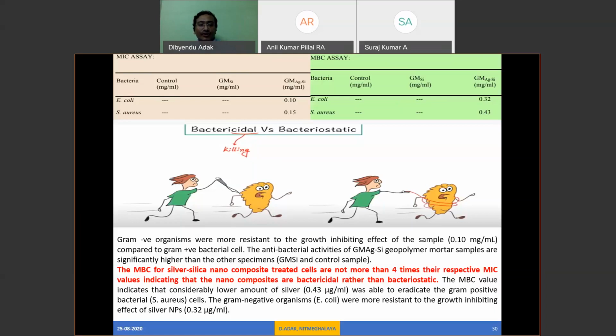So from this MIC and MBC, we can say that the silver silica nanocomposite treated cells have an MBC value not more than 4 times the MIC value. On these values, we can report that our nanocomposite is bactericidal rather than bacteriostatic. What is bactericidal? As I told you initially, the silver silica nanocomposite will kill the bacteria, whereas bacteriostatic means we can only make them stable and stop their rapid growth. Bactericidal means they will kill the bacteria. So from this MIC and MBC study, we can say that our silver silica composite has much more capability to kill the bacteria, not just stabilize their growth.